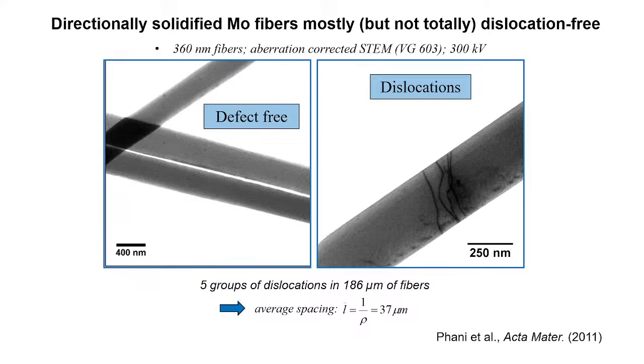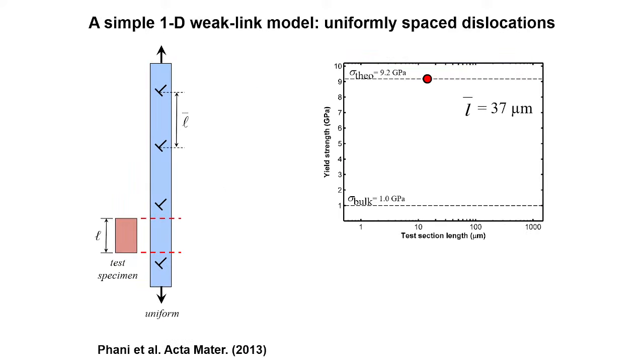Okay, so then the next thing he did was he developed a very simple 1D model for the tensile test, which I think is very clever. So there are, again, 2 length scales in the problem. One is the size of this pillar that you cut out, and the other one is the average spacing between the dislocations, right? And this, remember, is 37 microns because we measured it already, right? So if you cut a pillar from this region, you should get the theoretical strength. And if you cut a pillar including this, then you should get the bulk strength. This is a very simplistic picture where the bulk strength is equal to the critical resolved shear stress to move that dislocation. So you would go from either here, from here to here, right?